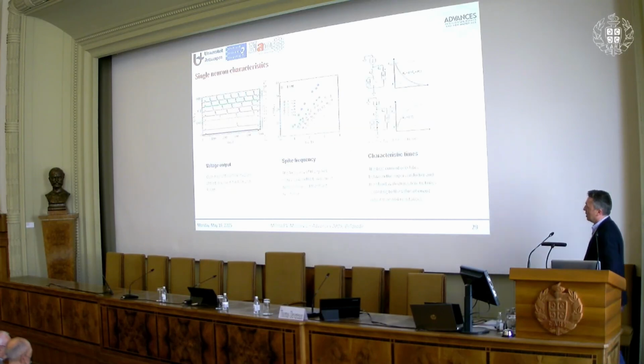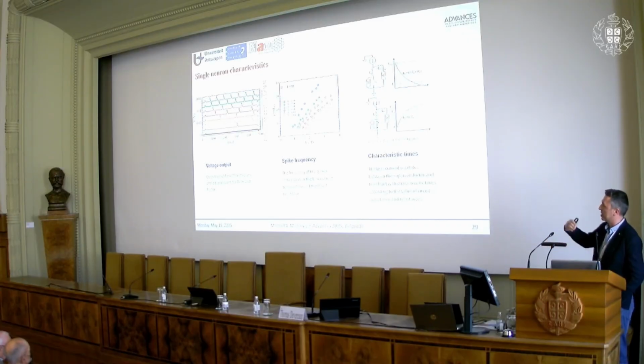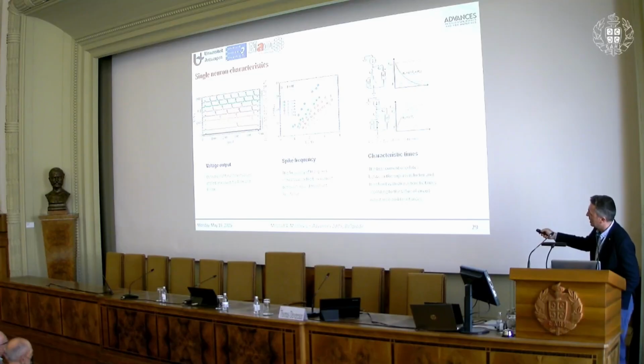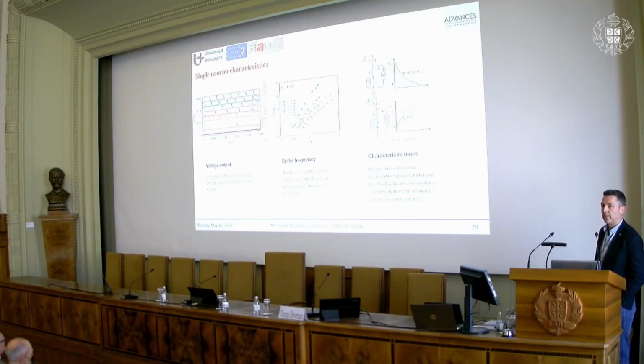So we did experimentally the voltage output. This is shown here as a function of applied current. We are just above the critical current, and we are increasing the applied current. And what you see is that in a fixed time of 500, actually the pulse is 400 nanoseconds, the current pulse, you see one spike, 2, 3, 4, and the number of spikes increasing.